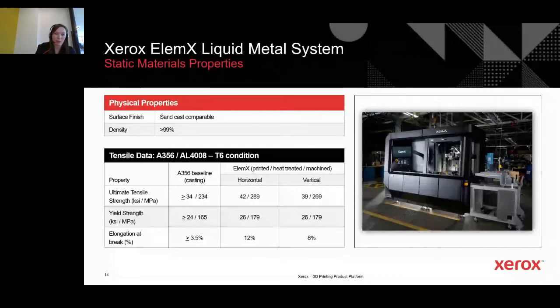And then you'll see some tensile data. So on the left, we have a baseline for A356 sand casting from the ASTM standard. And on the right is what we've achieved in printing. So this is still first generation technology. We're still developing, but as a metallurgist, I'm pretty happy with these numbers. We're above the baseline. Especially the elongation is pretty good. We do, of course, see some differences between horizontal and vertical orientation, which I think is fairly standard for the additive industry. But of course, we are working to understand what drives those differences and how we might improve our printer to improve upon those differences.